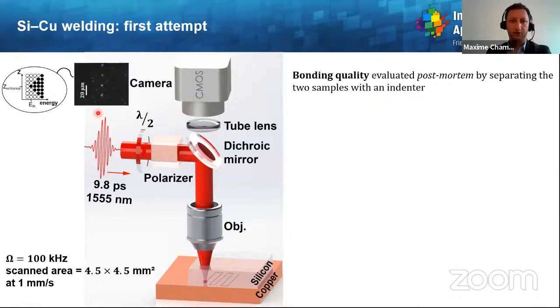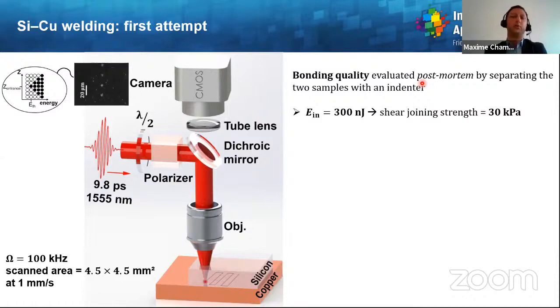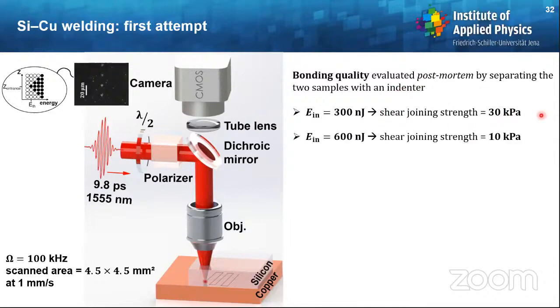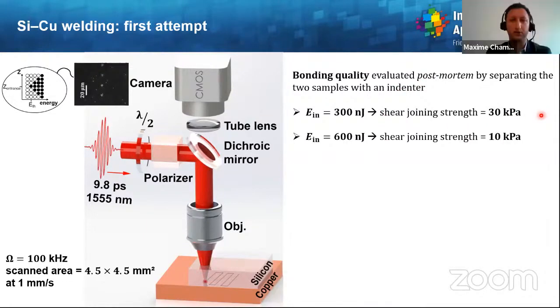Then after the laser processing, we evaluate the bonding quality in a post-mortem way by separating the two samples with an indenter. When we try with a relatively intermediate input pulse energy of 300 nanojoules, we can measure a shear joining strength of 30 kilopascal. Then what happens if we double the input pulse energy and go to 600 nanojoules? Then the shear joining strength is 3 times lower, 10 kilopascal.